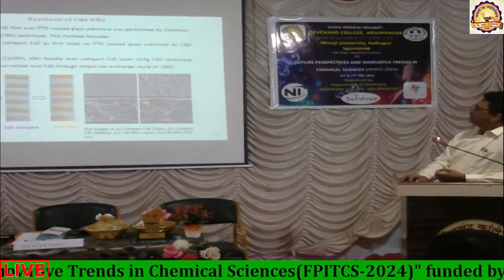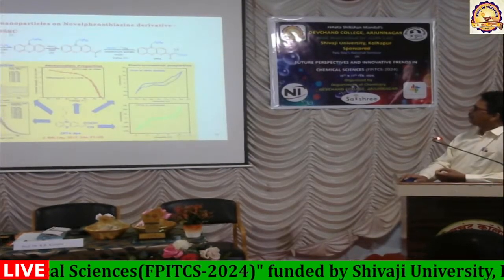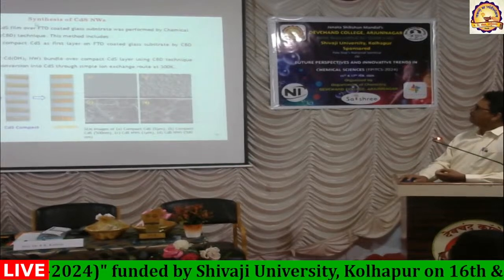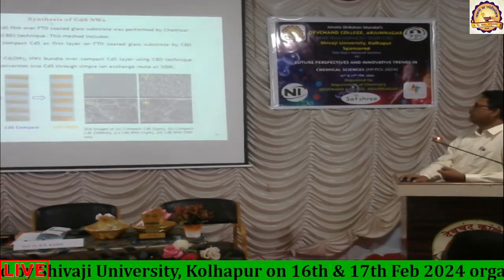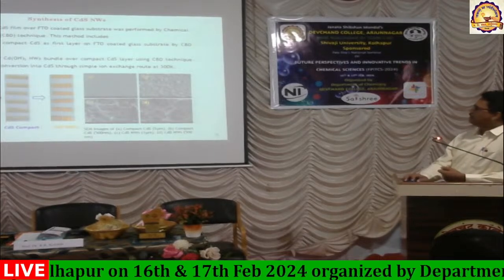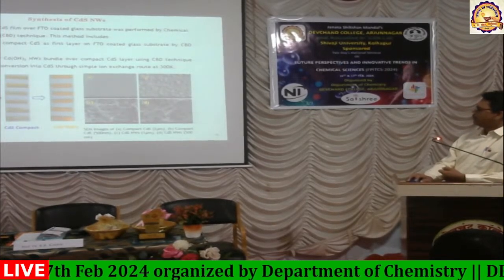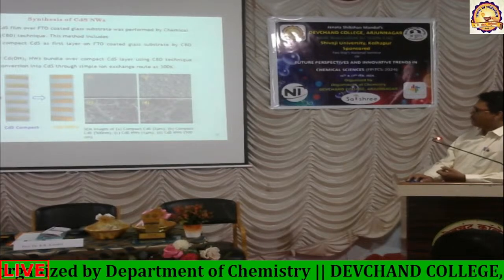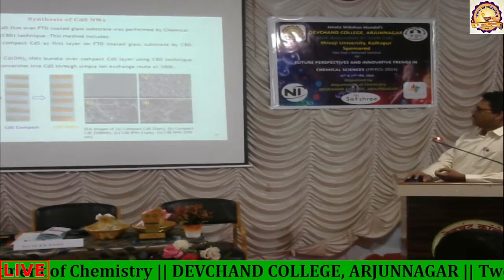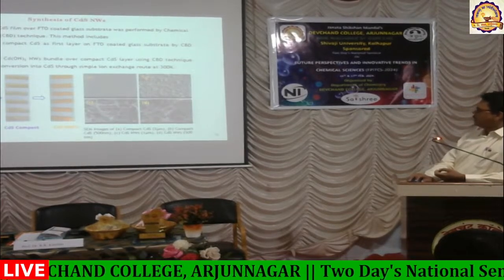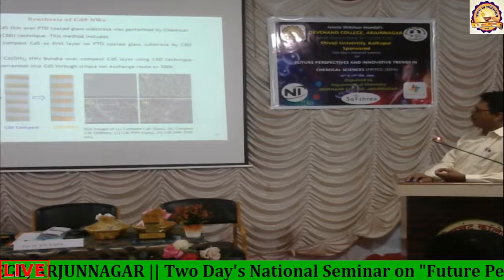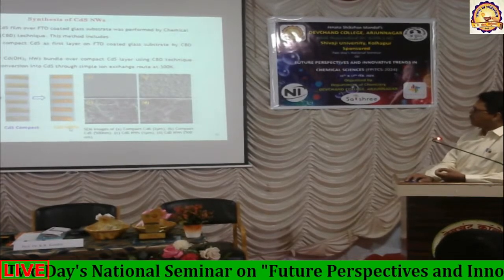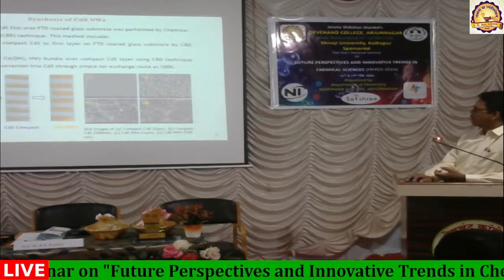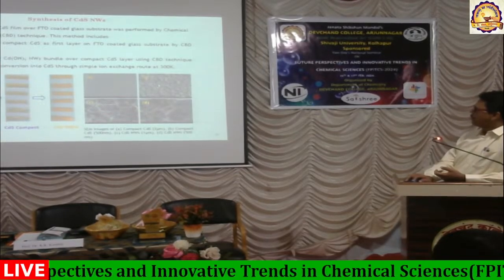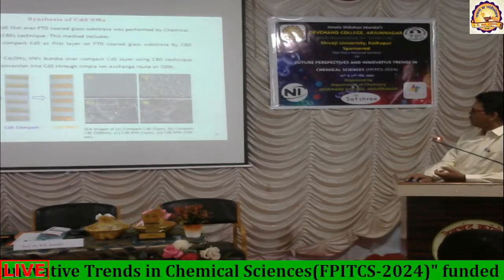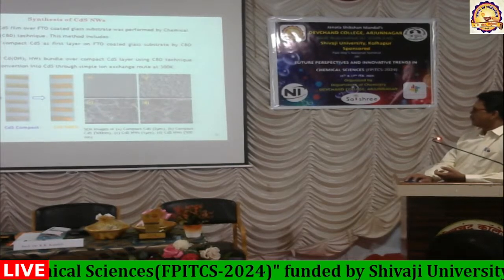Okay. So this was with the TiO2 nanoparticles we used. And then we tried, because we had one collaborator who was working on CdS nanowires, and we made use of his expertise, and we made use of CdS as a semiconductor, which used to accept the electrons from the dye. We made these CdS coated FTO, and then the CdS compact layer was introduced, and then CdS nanowires were introduced on this, and these are the images which indicate this is CdS compact, this is CdS coated, and this is the CdS nanowires.